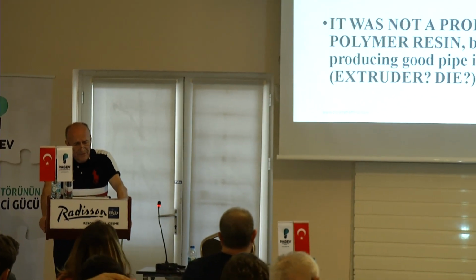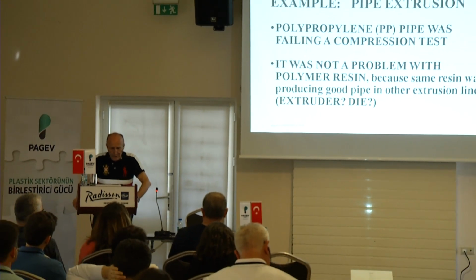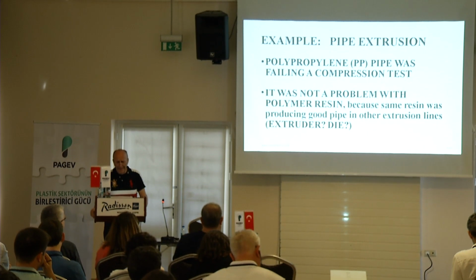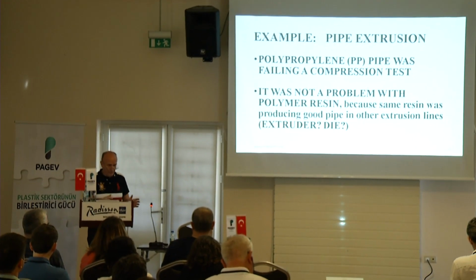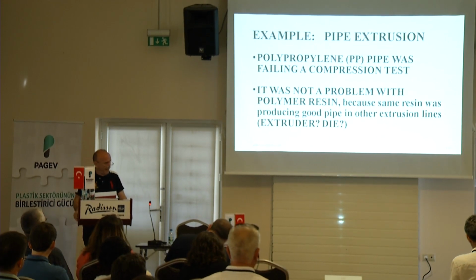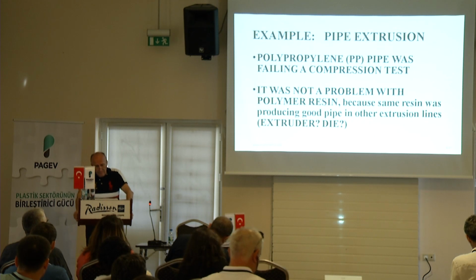Now, the biggest problem in extrusion is probably the unmelted polymer at the end of the screw. Probably number one. Second, probably poorly mixed materials that I mentioned. And third, degradation that is possible. Well, let me give you an example of pipe extrusion. It was in Europe, a northern European country. The material was polypropylene, and it was production of corrugated pipe, and the material was subjected to a compression test.